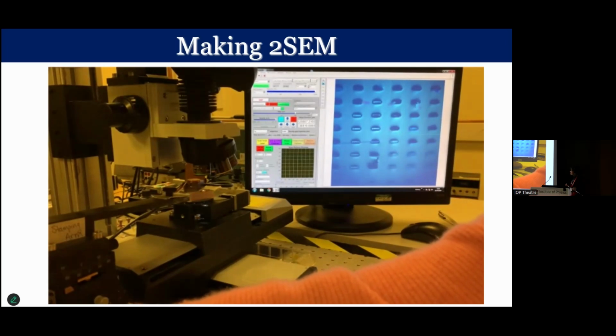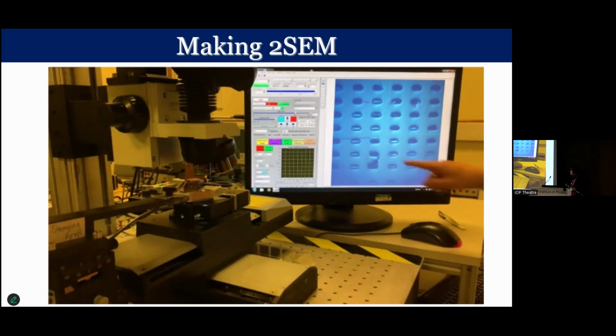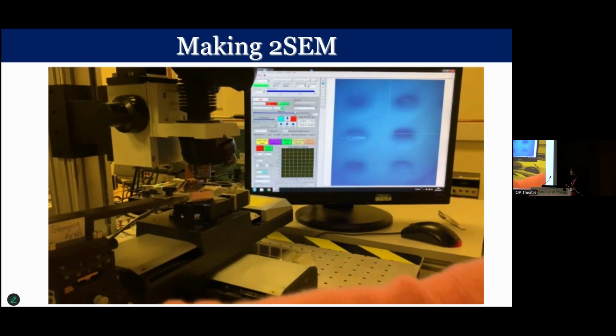This can take a few attempts of jiggling the needle around to get the PMMA on the top of the graphene to stick to the needle and completely dislodge it. Now that we have the graphene on the end of the needle, we can move it around to our desired location.